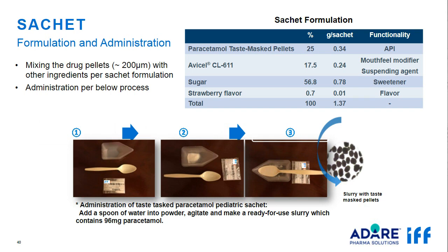Next, the coated pellets were blended with other ingredients. Colloidal Avicel CL611 was used as the suspending agent and mouthfeel modifier. For evaluation, 1 tablespoon of water was added to the powder and agitated before testing for palatability.